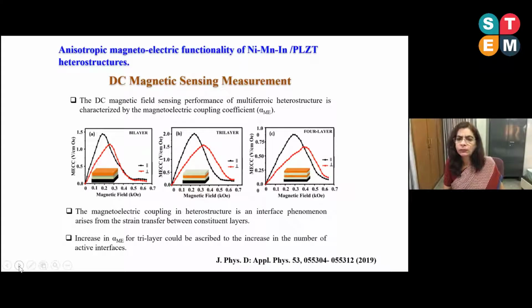The value of field up to which it is linear is useful for the magnetic sensing operation. We observed that when we go from bilayer to tri-layer, the value of the coupling coefficient increases, but as we go to the 4-layer, the coupling coefficient decreases.